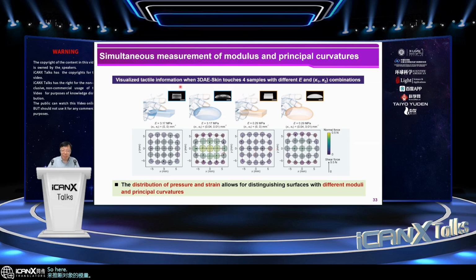So here, this slide shows the visualized tactile information when the 3DAE-Skin touches 4 standard samples with different combinations of elastic modulus and curvature components. So the first 2 samples are made of the same material, but with different shapes. This is flat, and this one has an ellipsoidal shape. And the third and fourth samples are made of a softer material with a modulus of 0.29 megapascal, and also two different shapes.